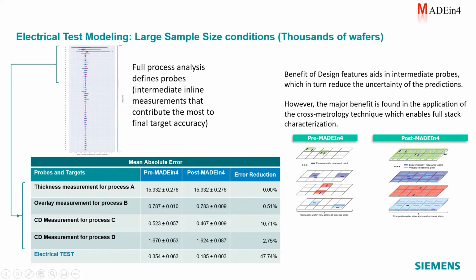But if we are able to fill in the blanks by creating all of these intermediate models, then the model can be concatenated in order to explain a final observation, and we can see that there is an error reduction of about 47%. This is significant because what this is saying is that by having the same number of physical measurements, we can fill in the blanks, generate those intermediate models, create a model that utilizes those virtual measurements, and improve our accuracy by 47%.